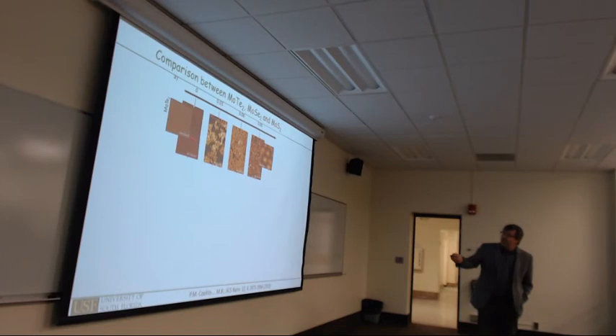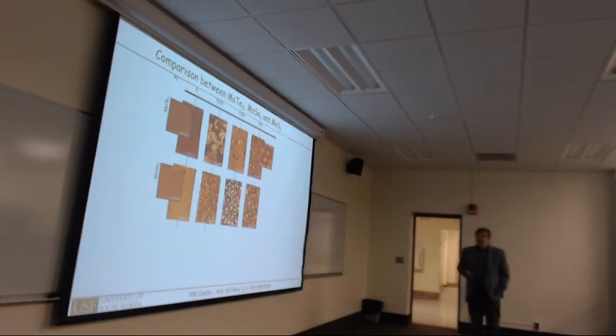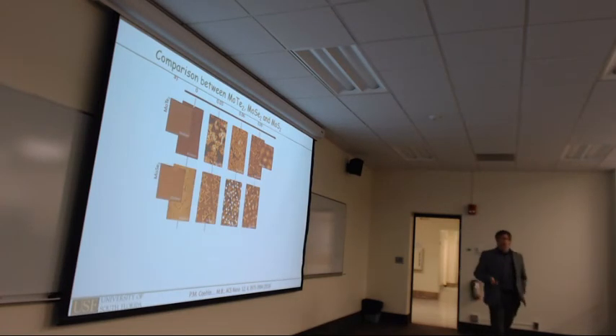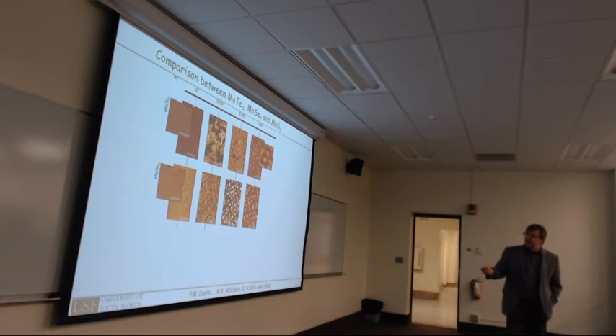So this was molybdenum ditelluride that I just showed. You can zoom in and show that these are these twin grain boundaries. We can do the same on molybdenum diselenide. Now on molybdenum diselenide, it has different kinetics.